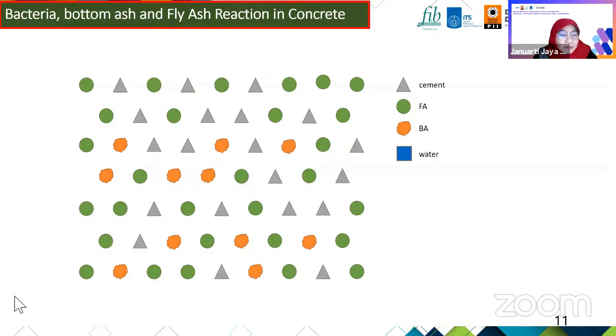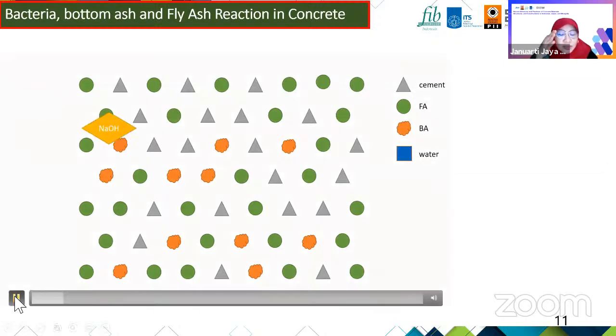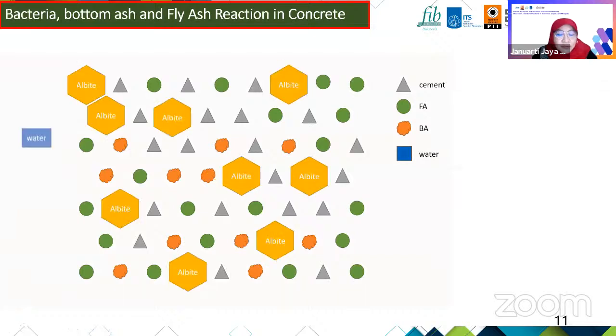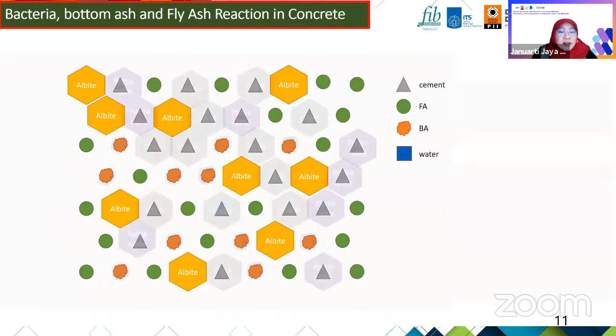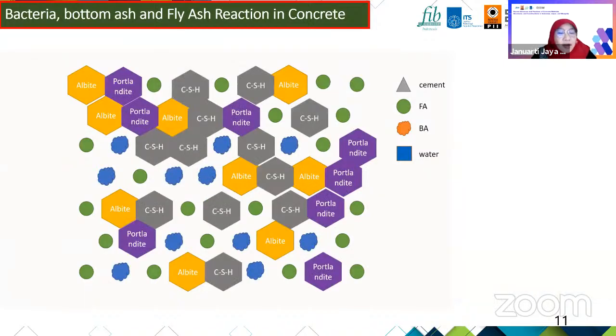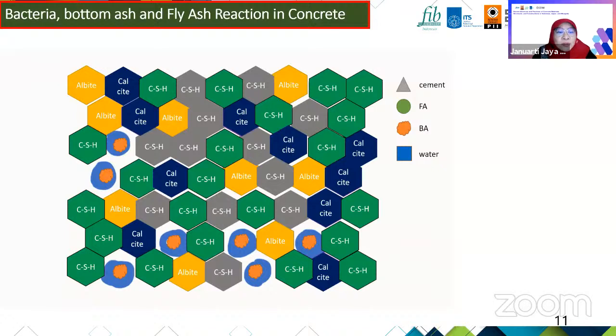And this is a bit complicated, but I tried my best to make simulations. This is the schematic reactions during the first hydrations at the later age of the concrete using bacteria, sodium hydroxide, and the coal ash. And the bacteria produce the CO2, react with the portlandite to produce calcite, and also the fly ash reacts with the portlandite to produce new calcium silicate hydrate. And at the end, we have a denser concrete, and the bottom ash here is still working to guarantee the internal curing inside the concrete during the hardening process.